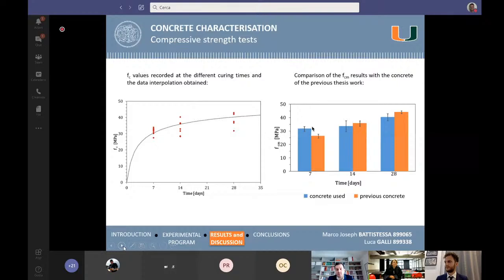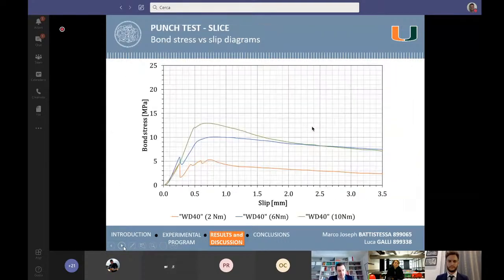You can see that after our first quicker development of mechanical properties in the concrete we used, we got very similar results at 14 and in particular 28 days of curing with values around 40 megapascal. From this point of view, it appears evident how the two concretes are comparable.